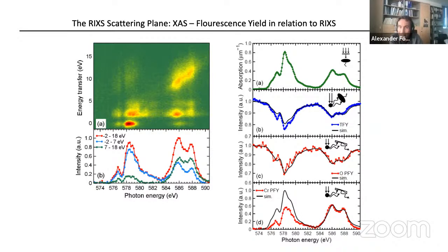I see. Because typically these scattering resonances are rather weak. There is a topic of the so-called shape resonance in XAS, and it's usually powerful, but it usually is the first scattering resonance, right? It's the next neighbor, and the next neighbor everybody has on the agenda, typically about 10, 15 eV above the lowest state. And this is why you go a little higher and then you're done. The fact that here we have to go significantly higher is